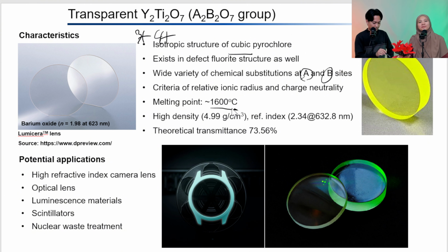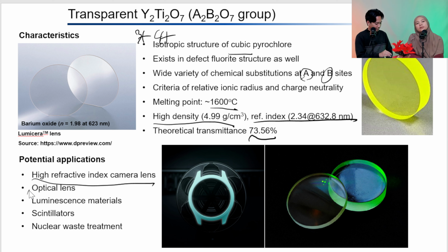But the most important properties of this material are its transmittance, high density and high refractive index, like 2.3. It's too high. Yeah, 2.3. It's much higher than gamma AlON that we talked about previously. And because of its higher refractive index, the theoretical transmittance should be lower, because of more reflectance on both surfaces. It was 85 for gamma AlON, and this one 73. But because of this high refractive index, it has very high potential. So far, it's not being produced or used commercially, but it has very high potential for high refractive index camera lenses, optical lenses, and many other applications also.